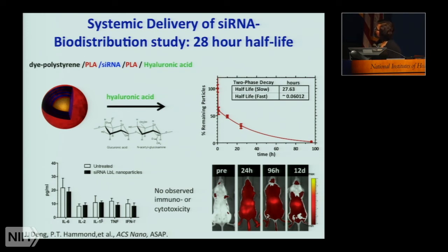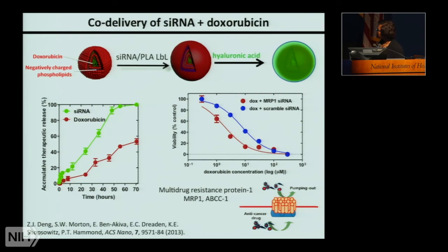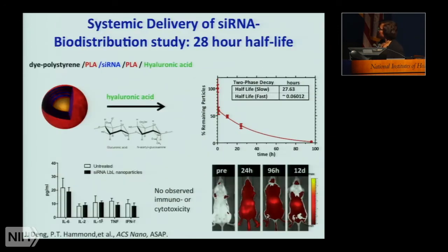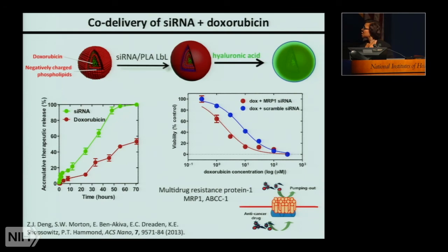The size of these nanoparticles is 120 nanometers. I should also mention that we didn't observe any kind of immuno or cytotoxicity. We did, of course, use a fairly simple panel of cytokines to examine that. If you look at the release characteristics of the nanoparticle, once again, we see the staggered effect. We can release siRNA over a more rapid time period of about 24 hours.